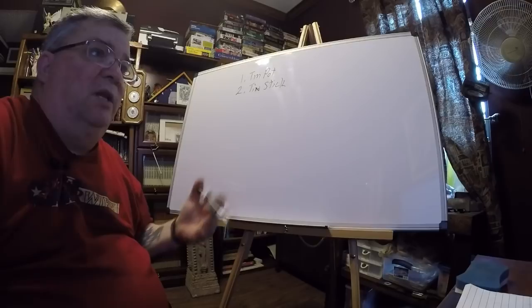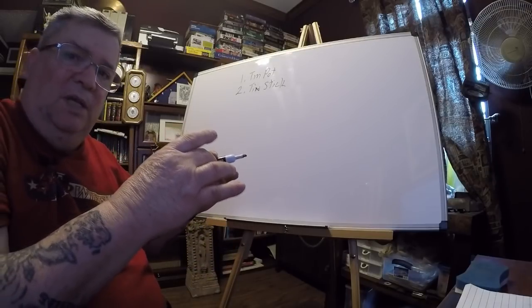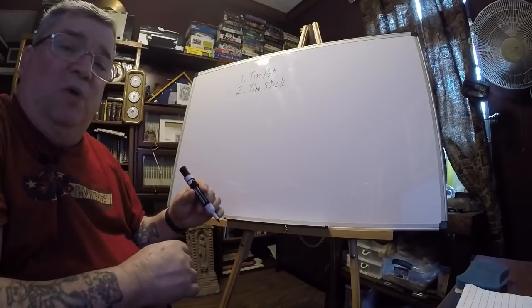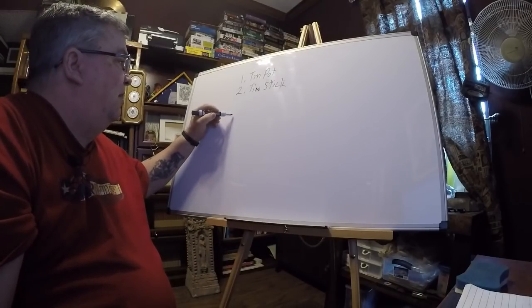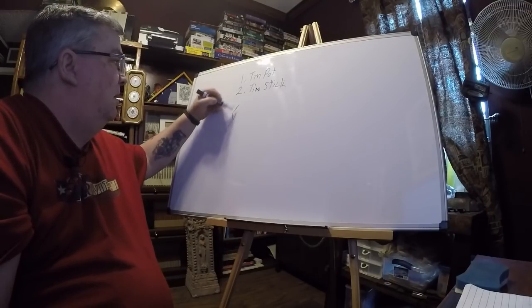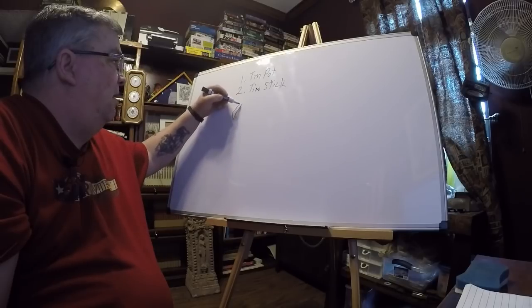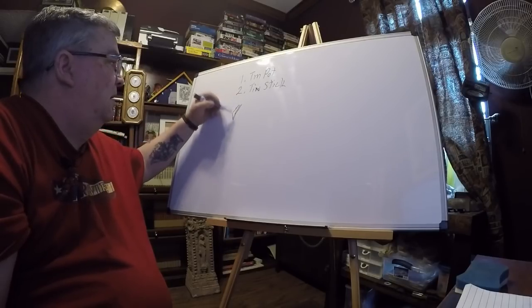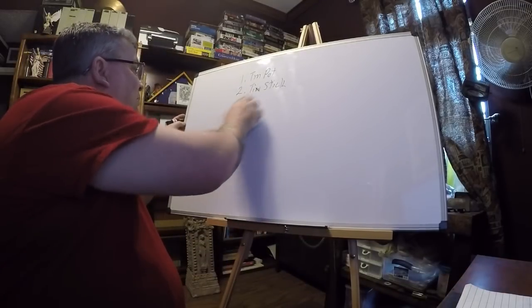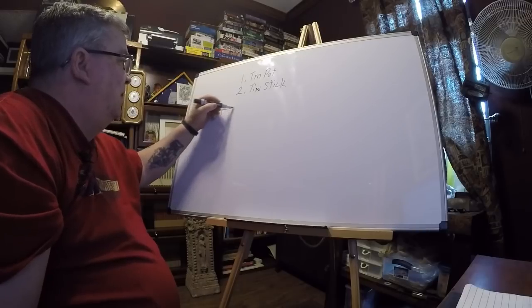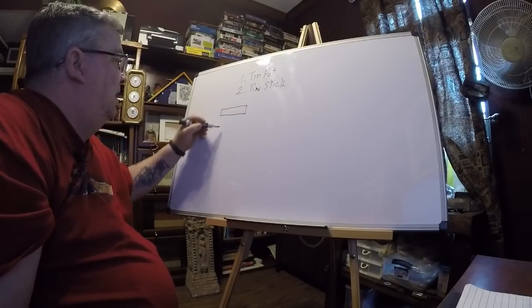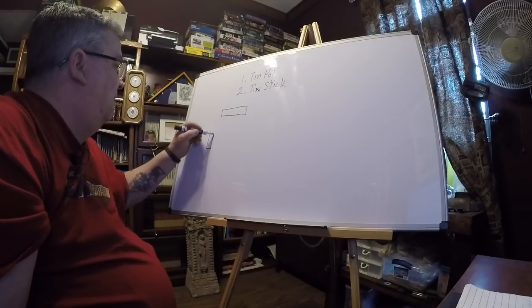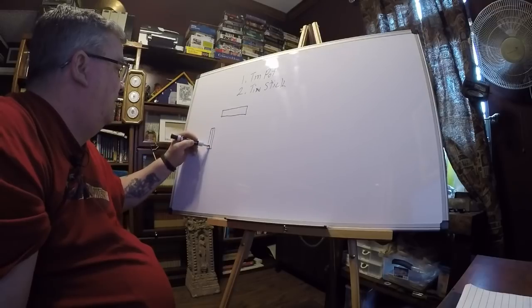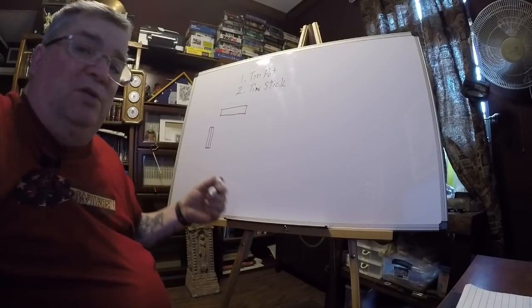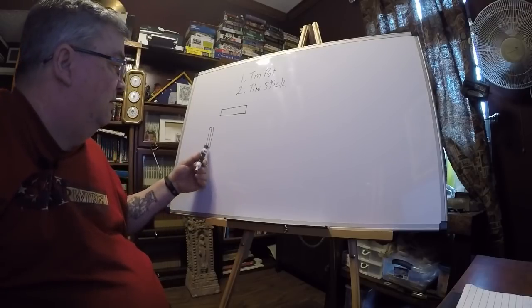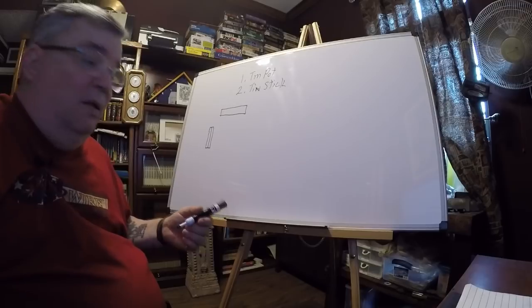Second, the one we usually did, is we usually had a tin stick. Usually when you buy tin, you'll get it in ingots. What we wound up doing is that we would have a piece of small angle iron. Let's just do it this way: a side view of the angle iron and a top view of the angle iron. I can do that much easier. We would just get 1-inch angle iron or 3/4 inch angle iron. It didn't make any difference.